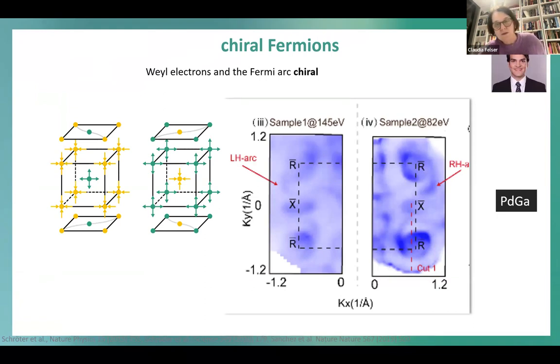and this was investigated by several groups also. This is here with Neil Schröter on palladium gallium, I think. And it shows nicely that one Fermi arc goes in this direction while the other goes in the other direction. Okay, they are really chiral. It's a little bit difficult to see. You need a little bit of fantasy, or you have to believe me.